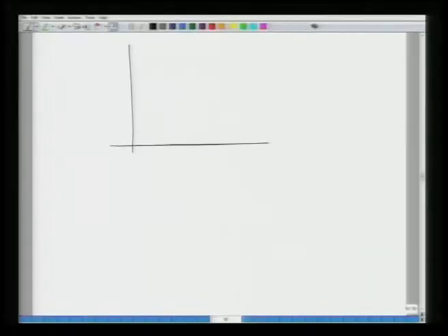So when you plot the vacancy concentration as a function of 1 by T, N here would mean the N_v concentration. The intrinsic vacancy concentration varies like this as a function of temperature, and this slope will be equal to delta H_s star divided by 2k.